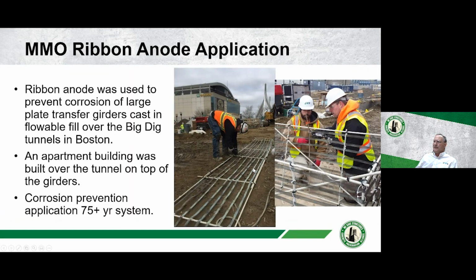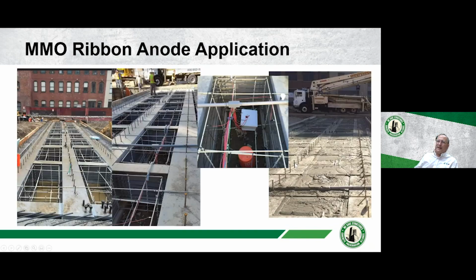Here's another unique application. This is over the Big Dig tunnels in Boston, and we had a set of transfer girders that was to hold up apartment building columns. This is directly over top of the tunnel. And you can see here we used fiberglass reinforcement to make a cage, and we tied our ribbon anodes to these cages, and these cages go inside. Here's the transfer girders. These cages went inside these little pockets. These were all filled with flowable fill.